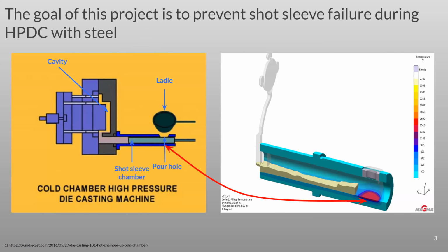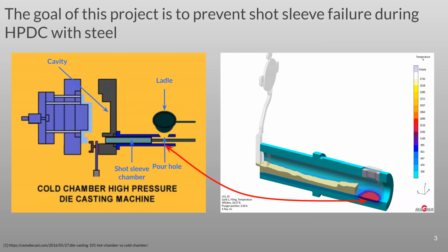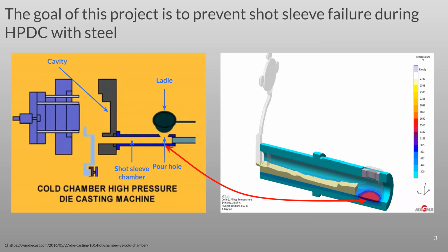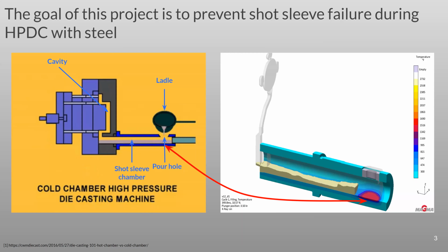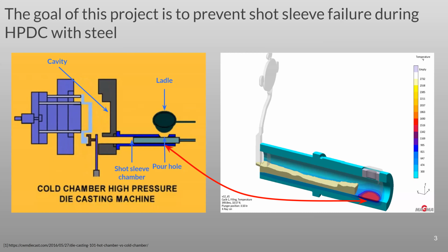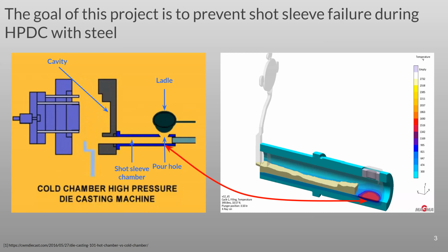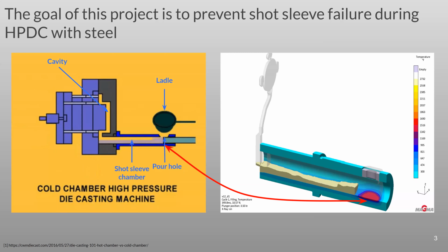During steel high-pressure die casting, molten steel is poured into an H13 shot sleeve where a copper beryllium plunger pushes the molten steel into a die cavity. The problem we are seeing is the high temperature of the molten steel being poured is causing the H13 shot sleeve to have a concentration of heat directly beneath the pour hole, increasing the temperature during each cycle until it melts and fails.